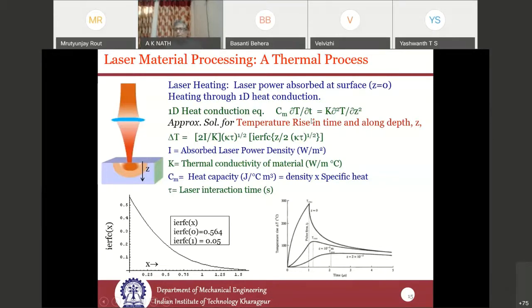Though it can be done numerically to get the temperature distribution in time and space, one can also get an approximate solution using this set of equations. This equation depends on the absorbed laser power density, thermal conductivity, kappa as the thermal diffusivity, and an error function whose nature is nearly exponential but slightly different, with values given like this.